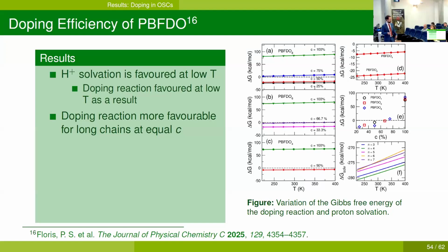when we increase the chain length, we are also increasing the conjugation length, which means reducing the band gap and making it easier for the polymer to be doped. Second thing to note is that when we look at delta G as a function of doping concentration, we see a steady increase for concentrations up to 75, 80%. And then there is an abrupt increase for concentrations higher than that.